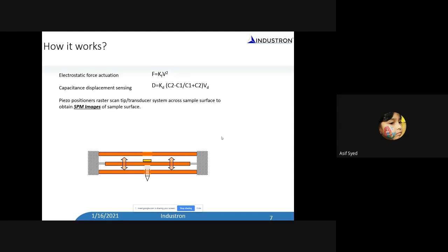So you have this three-plate capacitance structure. The center plate is supported by a spring so that it can move up and down. And these gaps are very small. The gap between these three plates is about 50 to 60 micron. Now, if you apply a high voltage at the bottom plate, it will generate the electrostatic force, and this center plate will get attracted to the bottom plate. That is how you generate the force. Now, if you put a tip into the center plate, and the tip is in contact with the specimen, then you can apply the force onto the sample and measure the displacement.